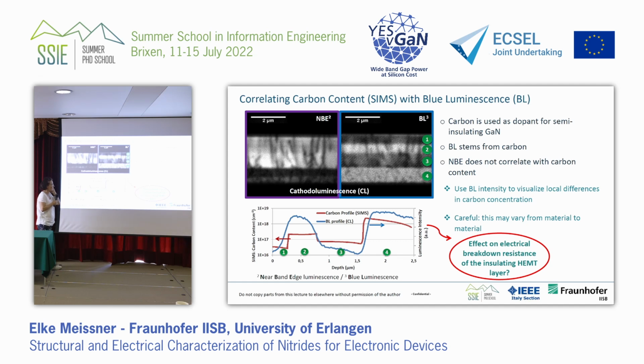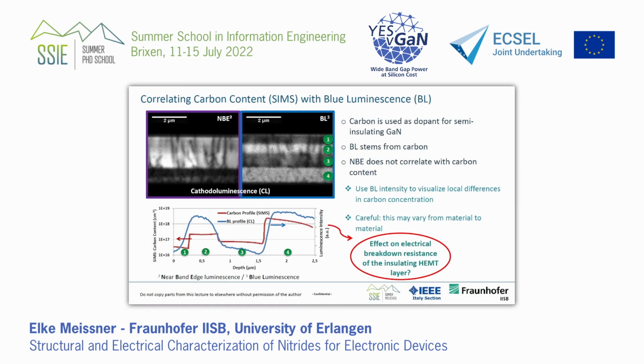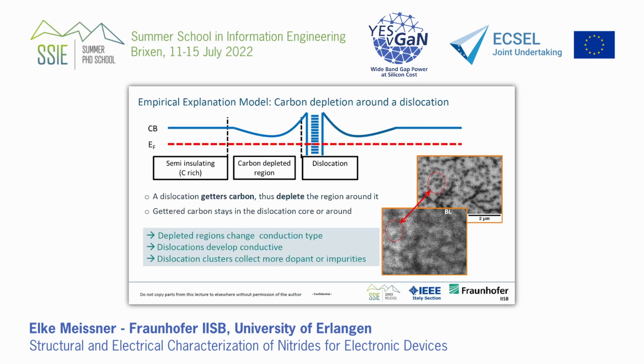And I showed you that we can monitor the carbon content, and we observed the blue luminescence. And we observed what we call the near band edge luminescence. It's close to the band edge, and it contains a lot of, let's say, levels in the band gap. And we saw that the blue luminescence, in this case, it's not always true, but in this case, monitors the local differences in carbon content. And we proved this by SIMS that what we measured, the blue luminescence profile, is in nice agreement with the carbon SIMS profile. So we monitored the blue luminescence in such samples from a plan view image.